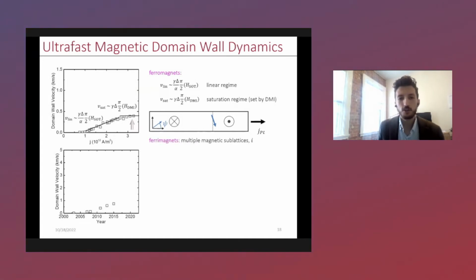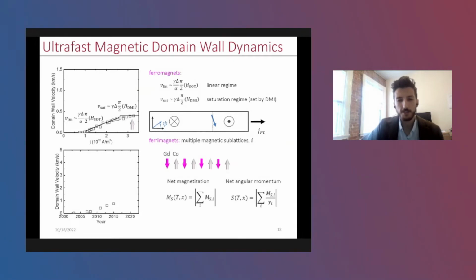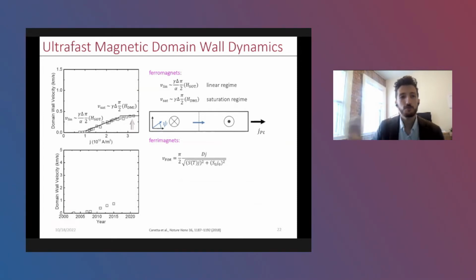So luckily, a few years ago, our group, as well as a few others, discovered that just by changing the magnetic material system you're using to something that's more compensated, like a ferrimagnet with multiple magnetic sublattices, you can overcome this. So one common example is to use a rare earth transition metal alloy, where you can easily control things like net magnetization and the net angular momentum of the system by tuning things like temperature and composition. So what it turns out is these equations of motion, or this model, actually fundamentally changes when you use these types of materials. You can account for the net magnetization and the net angular momentum in these expressions up above, and adapt them. What you find is what's actually important is the angular momentum.